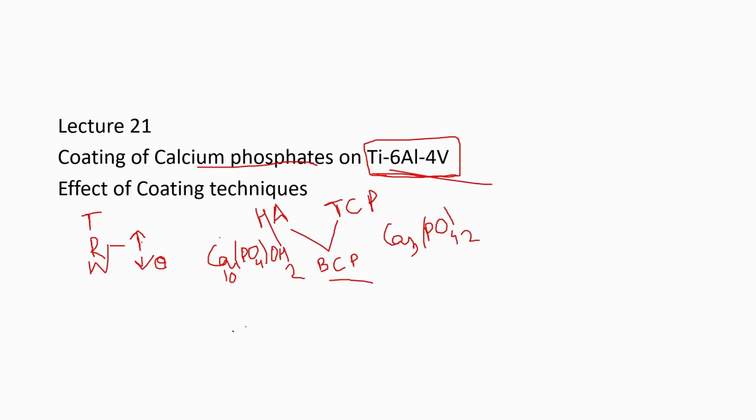And then they went on to coat the same implant with the same materials using laser cladding. Here hydroxyapatite as well as titanium hydroxyapatite mixture, both of them were used for coating. Titanium hydroxyapatite is more hydrophilic in nature. So these two were coated onto the surface by laser cladding. And again, the wettability and surface roughness, all those things were checked, and a higher surface roughness was observed with laser cladding.